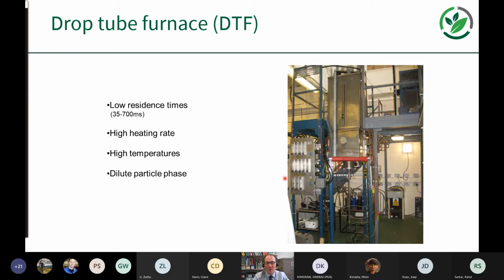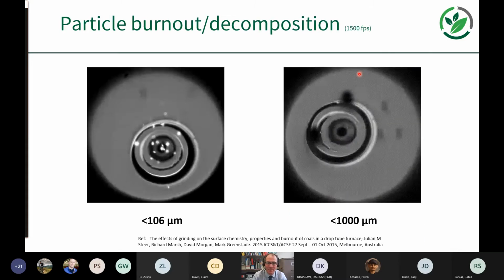So I've been using a drop tube furnace, and we use that to mimic this raceway region, this balloon-like bubble that's formed in the bottom of the furnace when you inject coals. And this gives characteristics which are similar to that raceway region: high heating rate, low residence times, high temperatures.